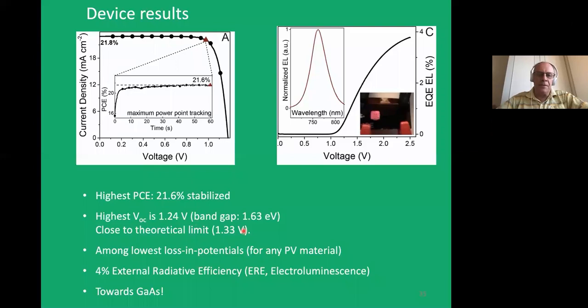Now, a good solar cell should also be a good light emitting device. So you can check this voltage by doing emission tests. So you reverse the solar cell to emit light instead as an LED. And that is done here. You see the red spot. That's a light emission device, and the electroluminescence was also at record levels at the time, around 3-4% efficiency, which also is a very high quality factor. So with that, we think even if we are doing it with very crude solution processing, we can get very high quality photovoltaic devices.